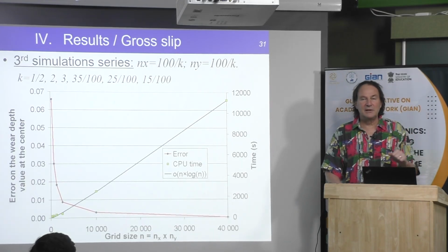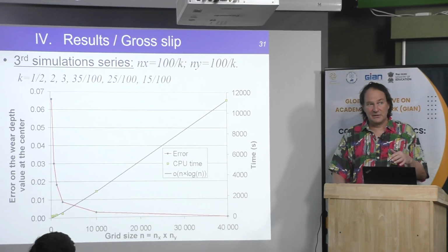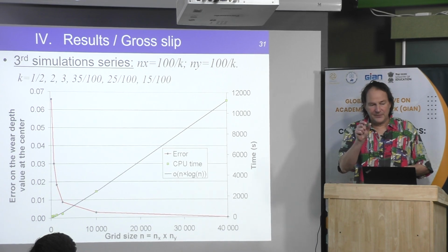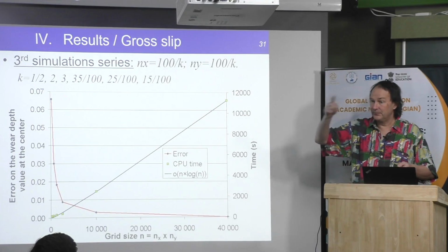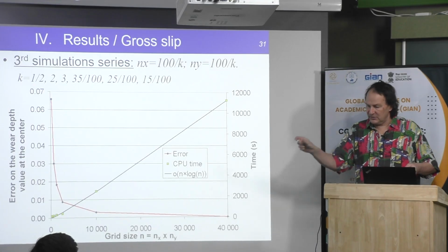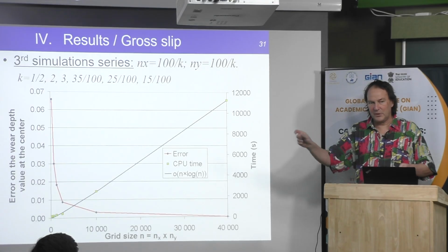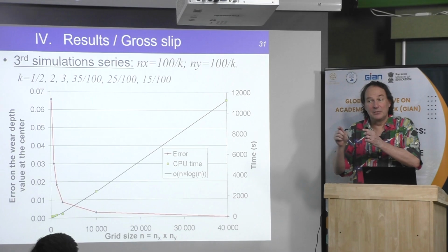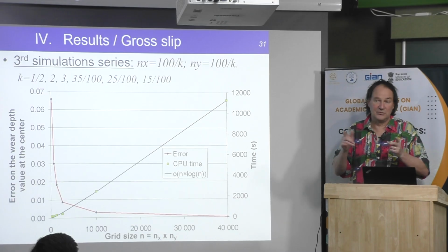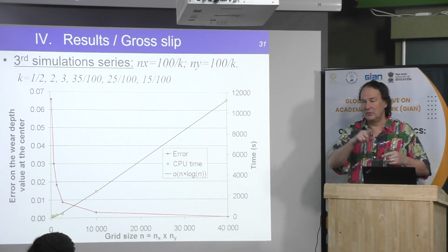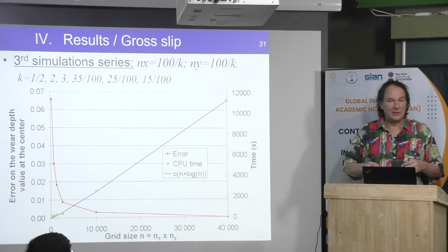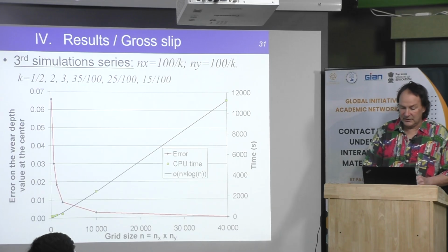Maybe a small detail. For those that are interested to simulate wear, there is two ways of doing that. You can do that cycle after cycle, a full cycle. For us, it is a way forward and back. But you can also simulate wear at each time step. Okay, but in fact there is no difference. It's better to do one full cycle than to divide a cycle in 100 time step. There is no interest to do that.